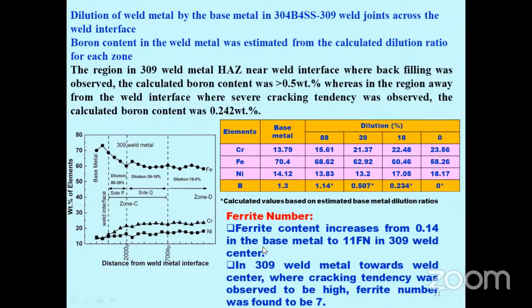So what is the purpose of going for the 309 electrode, which has a sufficient amount of delta ferrite? Here, though the ferrite number in this region is around 11, even then the cracking is occurring. This is because boron also has very low solubility in the delta ferrite that is present in the 309 electrode. So the delta ferrite or ferritic mode of solidification in this 309 electrode is also not helpful in mitigating the hot cracking in this borated stainless steel.